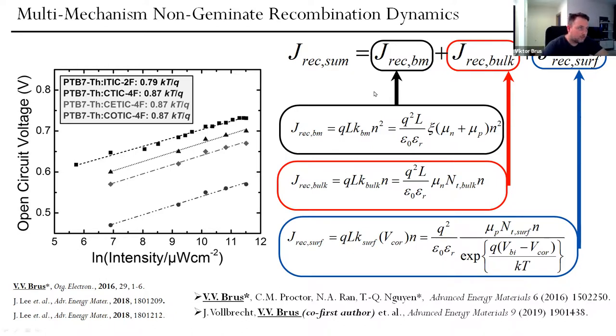which takes into account bimolecular recombination, trap-assisted recombination in the bulk, and trap-assisted recombination at the surface between the active layer and interface. And by combining all this, we can show that if we measure VOC, open circuit voltage, versus light intensity with a slope less than kT, like 1 kT over q, that means that we have some dominant surface recombination at the interface between the active layer and electrode.